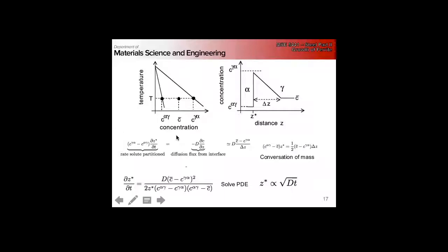Right. So basically, at a given temperature, we're partitioned by the lever rule. This is the textbook point down here, right? So this is the concentration of carbon in our alpha, concentration of carbon in our austenite, and we assume that the profile is going to look like this linearly. Here's our interface. So out in front of the interface, we have a higher carbon content. This is the carbon content of the equilibrium, right?